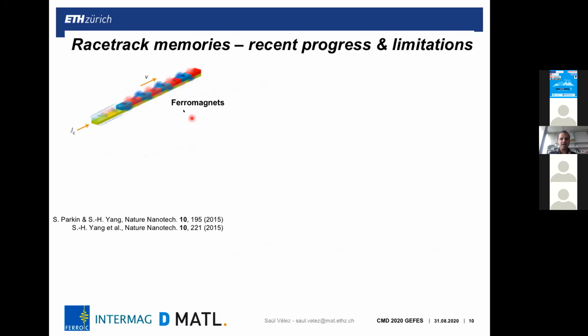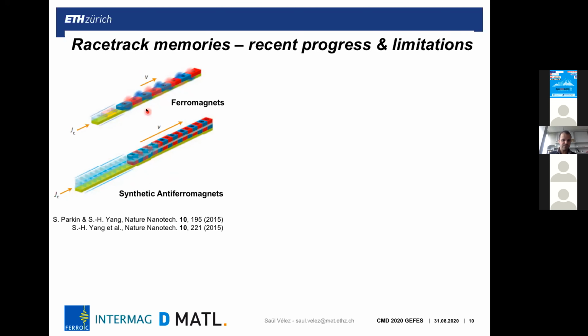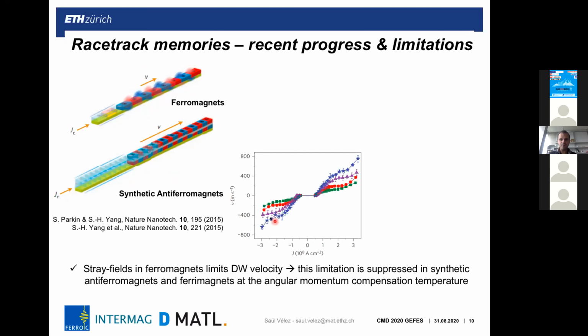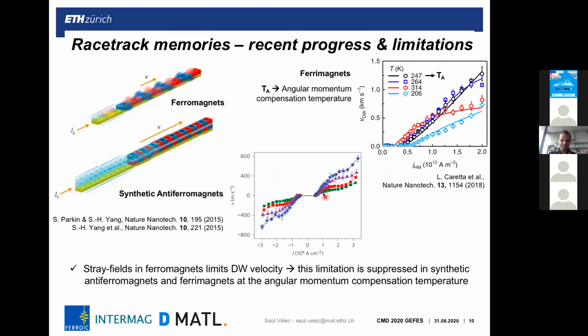So what are the limitations of these racetrack memories? The first that we have to think about is that in ferromagnets, you have stray fields which limit the domain wall velocity. But this can be suppressed, for instance, with synthetic antiferromagnets, in which, because of the absence of these stray fields, now you can drive domain walls much faster. By the time that this was done, the domain wall velocity was increased by a factor of 2-3. And you can also do this with ferrimagnets.